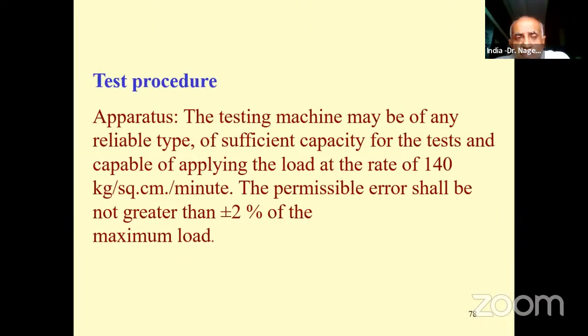Then the testing machine which we use shall be capable of maintaining a rate of loading of 140 kg per centimeter square per minute. The permissible error shall not be greater than plus or minus 2%. Nowadays, not even 2%, it is 1% only. If it is 2%, it is not a class 1 machine. If it is 1%, it can be called a class 1 machine. How will you get it? When you do the calibration of the compression testing machine, you will come to know about the accuracy of the machine.